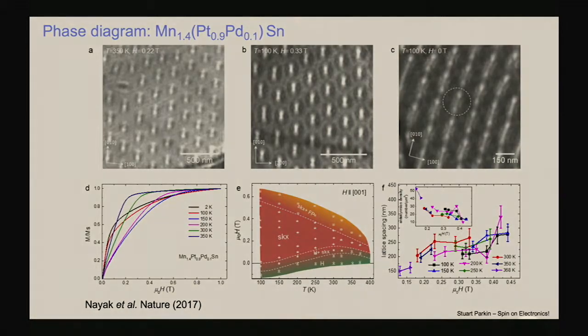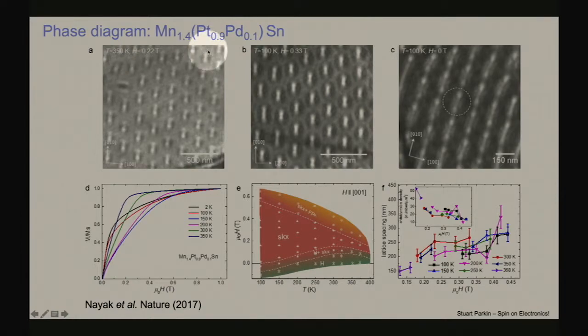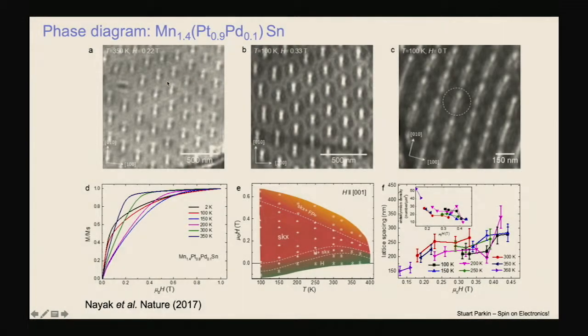It's not manganese 2 platinum tin, it's manganese 1.4, platinum 90%, palladium 10% tin. And this is for reasons that it's not possible to stabilize the material with all the manganese sites filled. The phase diagram is shown here. This is the temperature. The lowest temperature we can achieve is 100 degrees up to 400 degrees.